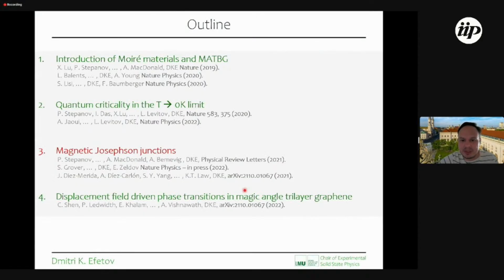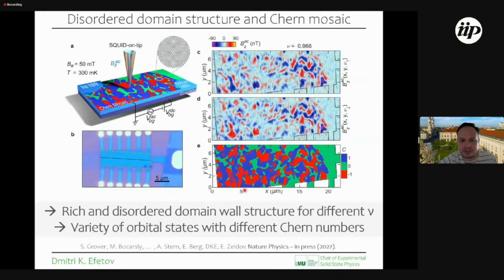Then the other thing is, we had one study here, which I haven't shown in detail, with Eli Zeldov, where we were able to map out these magnetic phases. And Eli worked out that those are really mosaics of Chern numbers forming there. So even if the device is clean, the magnetic domain structure is very chaotic. And they found a strong interplay between the different domain wall regions. In terms of theory, I'm sure you can find hundreds of papers on this, but I'm not too familiar myself.